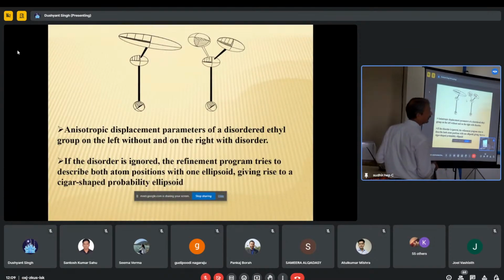If it is 5 to 10%, you can ignore it. If it is more than 20%, 30%, then you have to solve it and then refine it. If the disorder is ignored, the refinement program tries to describe both atom positions with one ellipsoid. If you try to ignore it, the molecule is spending some time here, some time here. It is vibrating. It may be orientation depending upon different orientations in different unit cells.